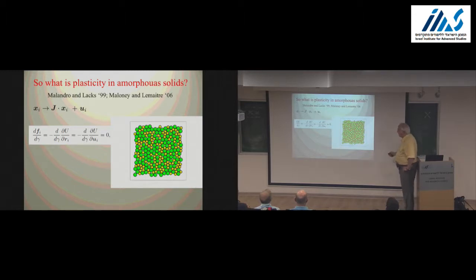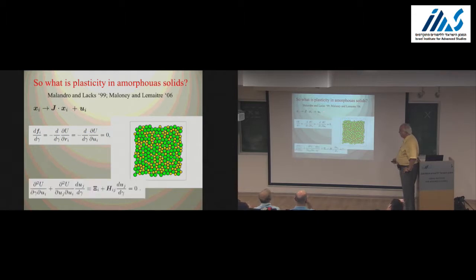Now, since this is a linear relationship between x_i and u_i to linear order, whether I take dU/dR_i or dU/du_i, it doesn't matter. So now let's interpret this double derivative. It has two contributions. One because U itself depends on gamma, and the other because the non-affine part depends on gamma. So I can break it into two contributions. U itself depends on gamma, so I get a partial derivative d squared U/(d gamma du_i), and then by the chain rule, since u_j depends on gamma, I have another term d squared U/(du_i du_j) times du_j/d gamma. And this has to be zero.